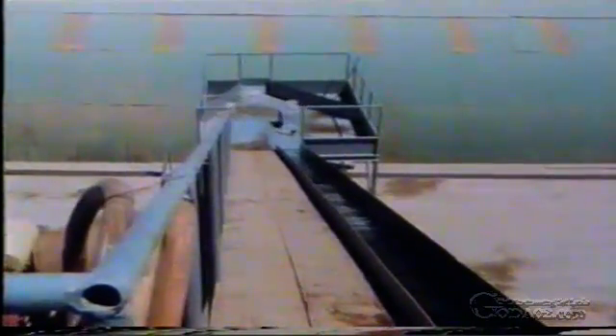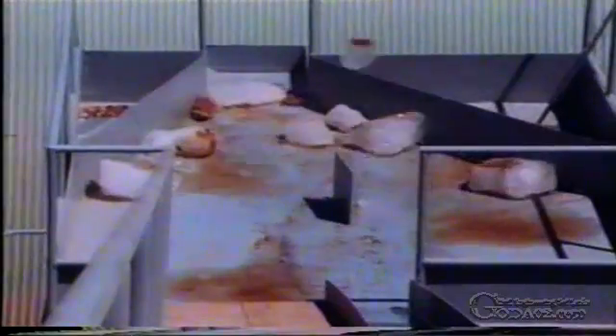The first step was spraying the aggregates with river water, that is, cooling by surface evaporation. A second step was the artificial cooling of the mixing water for the concrete, and a third step, which could be resorted to if necessary, was adding ice flakes to the freshly loaded transport vehicles. This meant that it was possible to adapt to the prevailing temperature and that the site could always be supplied with sufficiently cool, top-quality concrete.